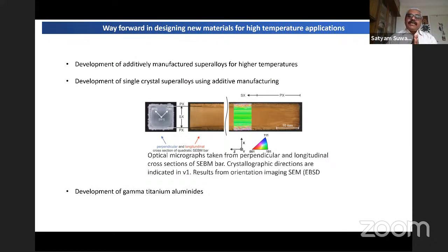some kind of a single crystal type of structure by the EBM process, which is again another attribute of all these gas turbine materials, right? Particularly for blades which are used in single crystalline conditions, because we can generate by controlling the cooling conditions, which are much better controlled in this case. We can very well control the orientation of these materials. So we have carried out this whole thing, and this has paved the way.